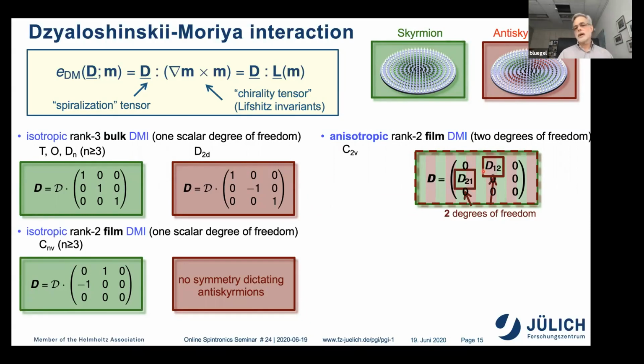For some people who maybe work in other fields, I would like to draw a relation. If you construct a microscopic electronic model to represent the Néel type skyrmion, then it would be a Rashba model. For the Bloch type skyrmion, it would be the Dresselhaus model. But here you have a symmetry which is a combination of Rashba and Dresselhaus. And since the Dzyaloshinskii-Moriya interaction has the same symmetry operation as the field-like torque, that means also in the field-like torque you would have two independent parameters.